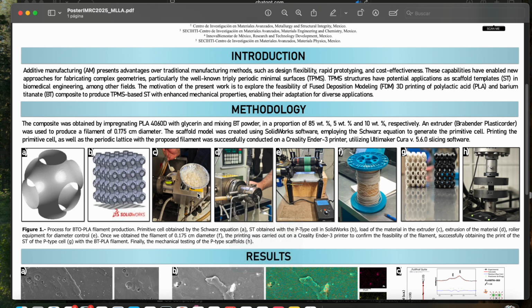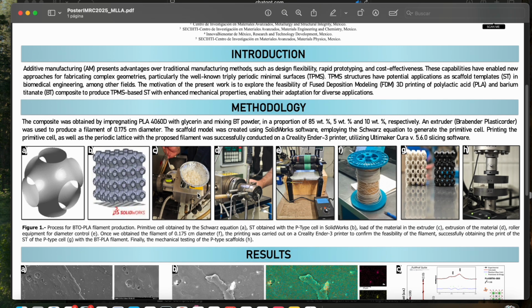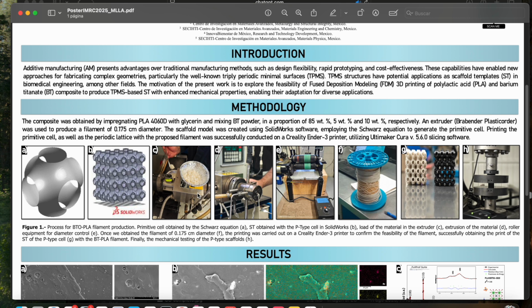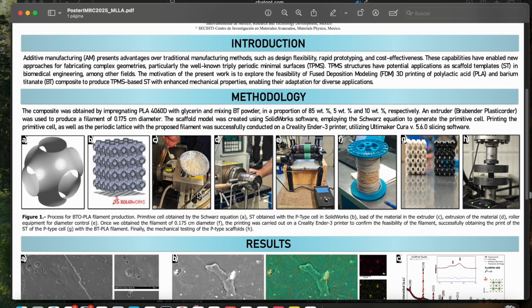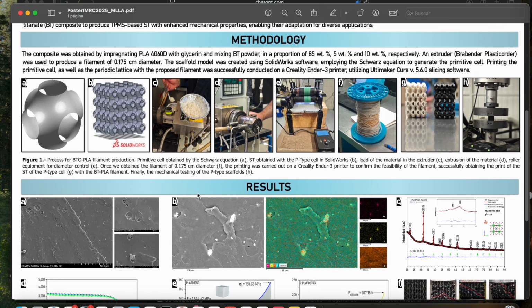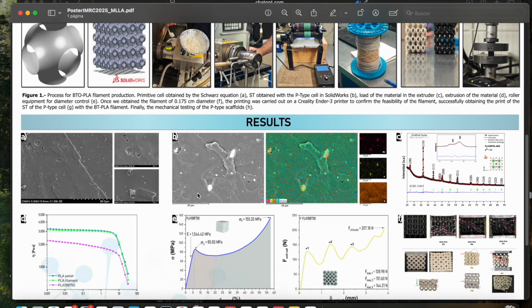The TPMS primitive cell was generated in SolidWorks from the Schwarz equation and tiled into a periodic scaffold that we used for compression tests. The composite structure and dispersion were validated by SEM, EDS, and XRD with Rietveld refinement. Cross-section SEM shows a rough PLA matrix containing BTO clusters, while global EDS maps of Ba, Ti, and O indicate an overall homogeneous distribution at the scaffold scale.